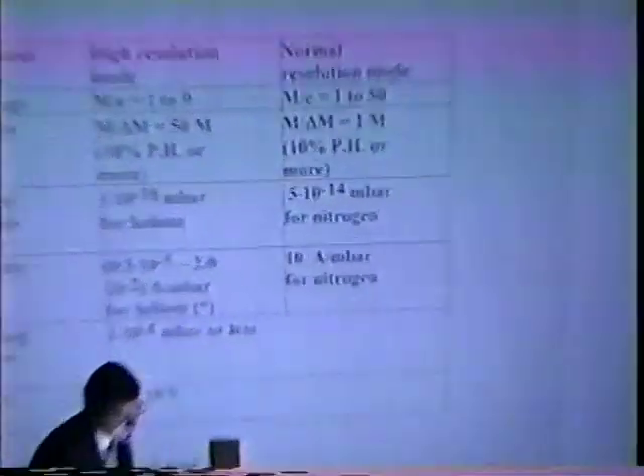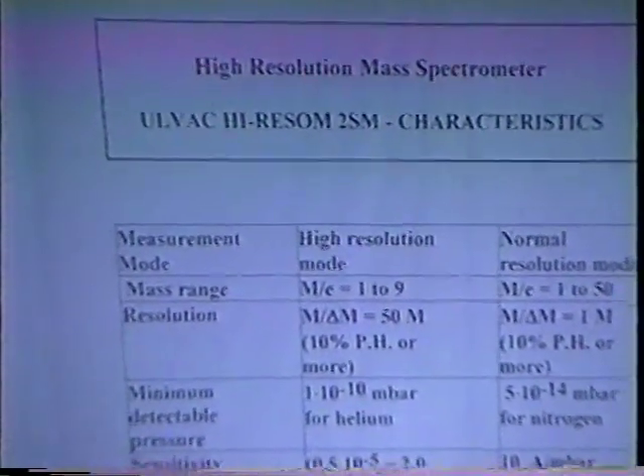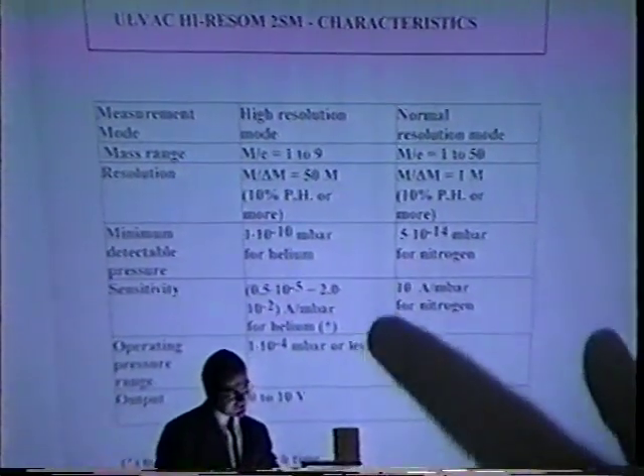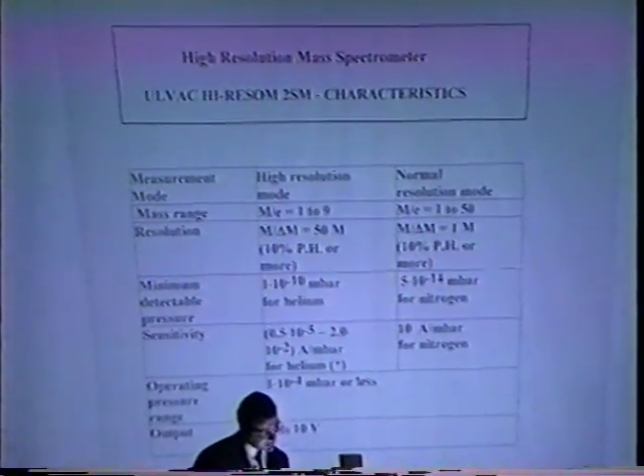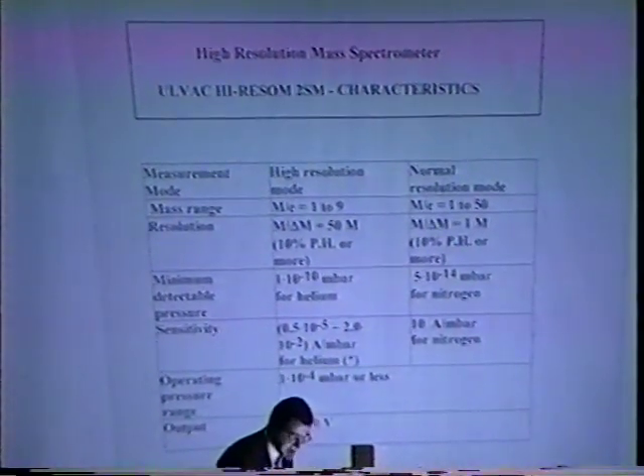What about the spectrometric apparatus? It's a high-resolution mass spectrometer built by ULVAC, whose main characteristics are reported in this table. The important thing is the sensitivity of the instrument, which has to be determined each time that we perform a measurement. So the values reported here are a rough variation range of the sensitivity that you can find during the operation. Given its importance, we performed several calibration runs before and after our measurements, obtaining for the sensitivity a value of 2.2 times 10 to the minus 4 ampere per millibar. That showed rather stable behavior with time of measurement.